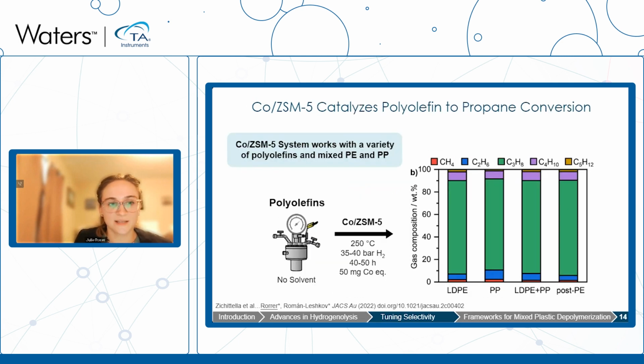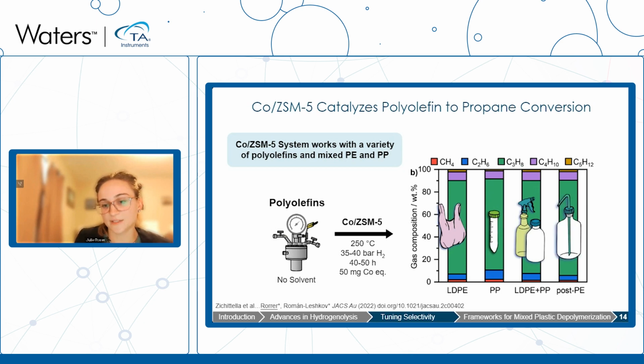And with this stable catalyst in hand, we can actually apply it to the conversion of polyethylene and polypropylene and of different types. And so here with our reaction, again, no solvent, 250 degrees C with hydrogen pressure, we can convert low density polyethylene into propane, polypropylene, mixtures of low density polyethylene and polypropylene, as well as realistic post-consumer polyethylene.